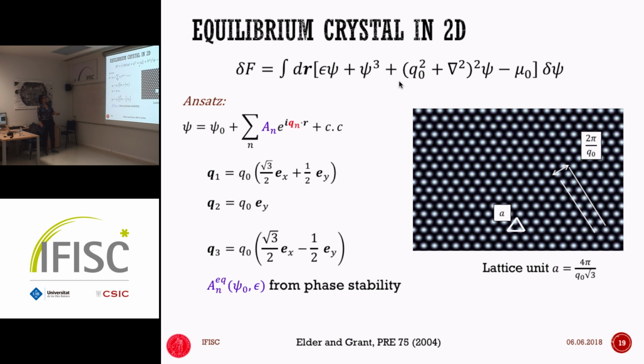We can focus on the crystals, the equilibrium crystals in 2 dimensions. So by minimizing this free energy at a given fixed density, we can get a hexagonal pattern. In 3D, it will be BCC patterns. Depending on how you tune this non-local term, and you can add another combination of higher order gradients to build up different kinds of symmetry. You can also have a cubic lattice in 2 dimensions if that's what you want. So there's a certain degree of freedom to play with this non-local term. But the point is that you have a crystalline structure by whatever means you want to derive it.